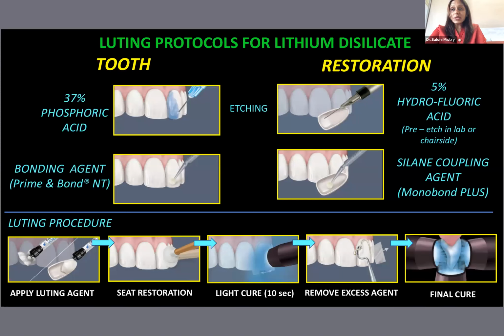After that, as I mentioned, the silane coupling agent has to be applied on the intaglio surface of the restoration. Then the normal protocol has to be followed. That means you have already conditioned the tooth with the bonding agent, you have cured it. Then you place the luting agent on the intaglio surface, you seat it, you light cure it for 10 seconds, you wait, you remove the excess cement, and then you finish your final cure. So this is the protocol which has to be followed very judiciously.